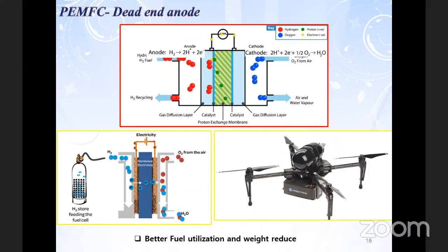And if the listener or the audience is from nanomaterials or working in fuel cell technology, they are aware of this situation: the hydrogen should not cross over. Okay, it should not meet the oxygen. If you increase the pressure, if you feed more hydrogen, it will break the catalyst layer and proton exchange membrane, and it meets the oxygen. And when it meets the oxygen, it can blow up your whole system, it is explosive. Okay, so we keep the pressure very uniform and as low as possible, and use the maximum hydrogen from here. And the oxygen is being sucked out from the air. Okay, and this is how we use the limited hydrogen.